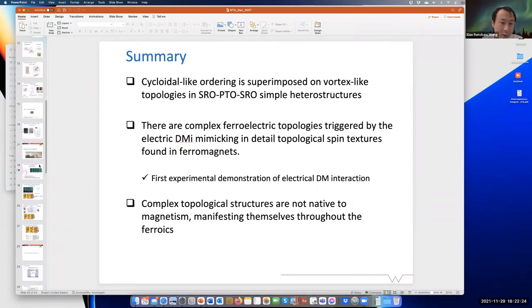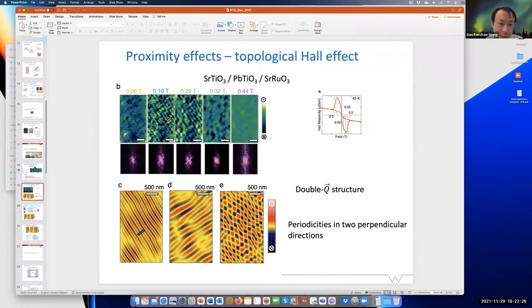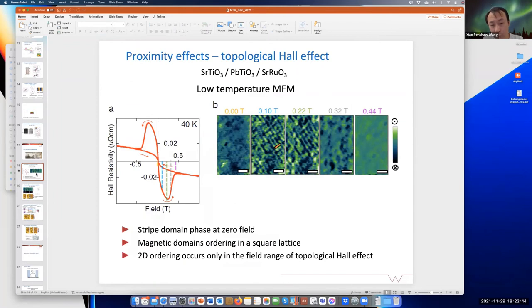As far as I know, there is a phase transition of strontium titanate at 105 K, from cubic to tetragonal phase. And also, if we talk about ferroelectricity, for PTO the TC is pretty high. You also mentioned that you want to do temperature-dependent measurements. How high a temperature can you go? Can you go above 105 K to see whether it's from STO, or about 150 K to see whether it's from strontium ruthenate? Sure.